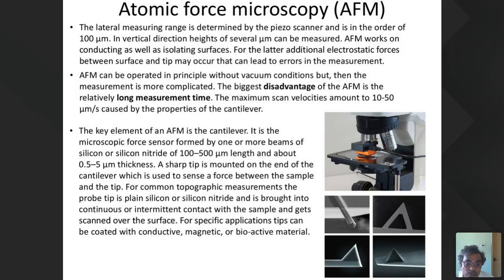AFM can be operated in principle without vacuum conditions, but then the measurement is more complicated. The biggest disadvantage of AFM is the long measurement time. The maximum scan velocities amount to 10 to 50 micrometers per second. Okay. The key element here is the cantilever.